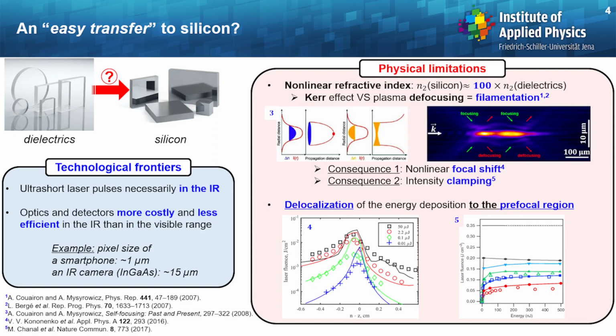Now, the main problem actually originates from physical limitations, especially when you have a look at the nonlinear refractive index of silicon. It is about 100 times higher than the one of glasses. What does it mean? It means that at relatively modest peak input pulse energies, there will be this competition between the Kerr effect, which self-focuses the beam, and plasma defocusing. So when you focus too tight, then a plasma is formed, and this plasma will defocus the beam, then refocus, defocus, and so on. This is what we call the filamentation regime.